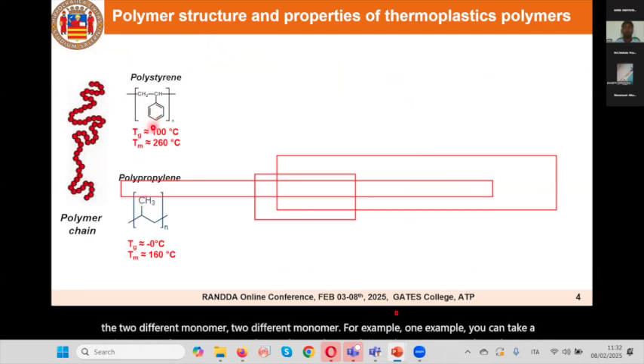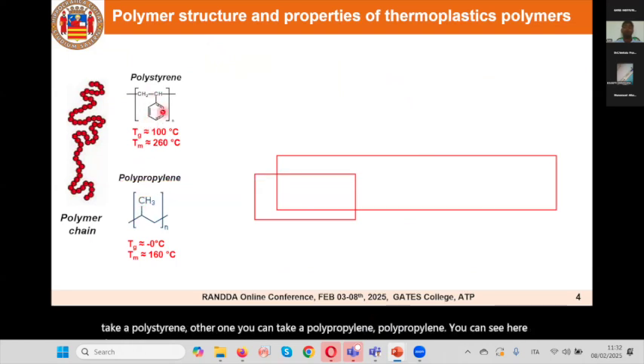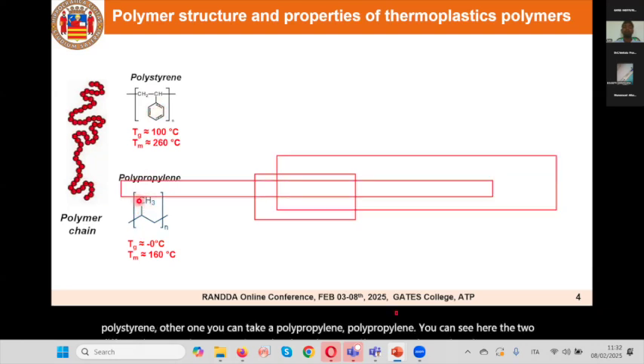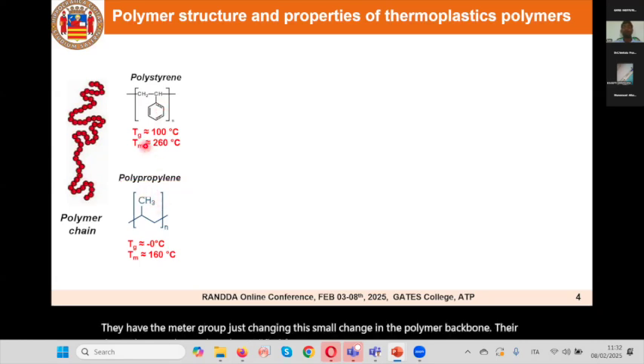You can see the difference between these two polymers is only a minor change. In one case there is a phenyl group, in the other case a methyl group. Just by this small change in the polymer backbone, their thermal properties are largely modified. For example, the Tg of polystyrene is 100 degrees centigrade and Tm is 260 degrees. Whereas in polypropylene, the Tg and Tm are 0 and 160 degrees respectively. So just by changing a small atom in the polymer backbone, their properties are completely changed. The difference is nearly 100 degrees centigrade. That much change you can see from a minor structural change in the polymer backbone.